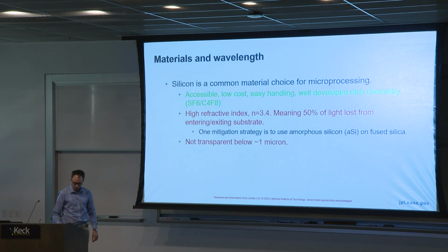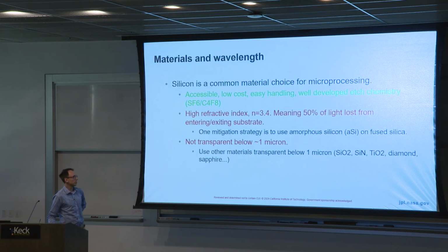I think another, more fundamental issue with using silicon is that it's essentially a piece of rock, and we know that rocks aren't transparent to visible light. It depends on the exact type of silicon that you use, but typically around a micron, if you go to shorter wavelengths, silicon is not transparent. So if you're trying to make a transmissive optic, that's not the greatest material. There are definitely people who have demonstrated metasurfaces below a micron, but especially if you hope to go into blue and even UV wavelengths, silicon becomes not a great choice. So you then have to move to other materials, and this is a very non-exhaustive list: silicon oxide, silicon nitride, titanium dioxide, diamond, sapphire, etc.